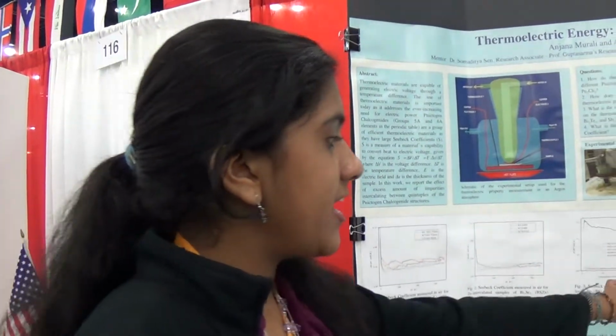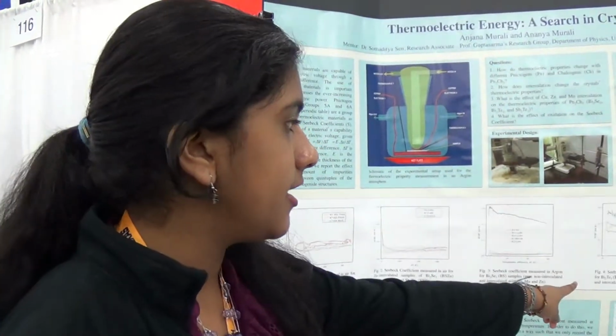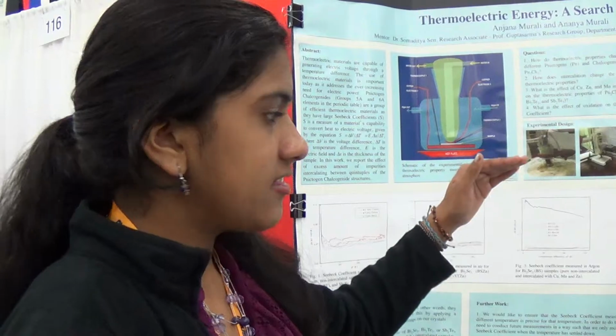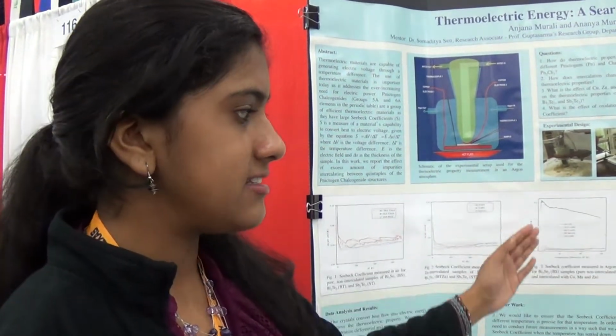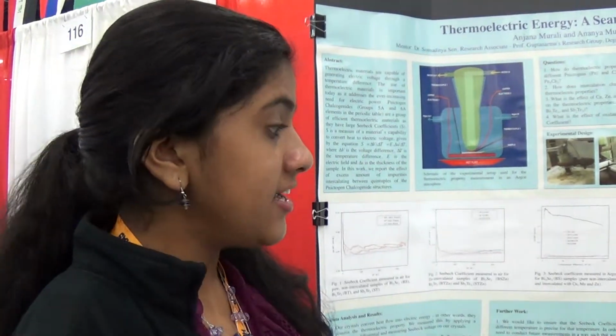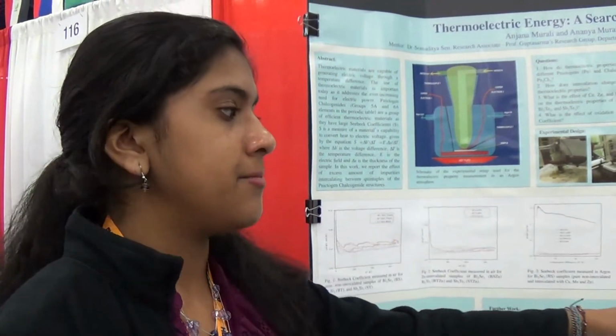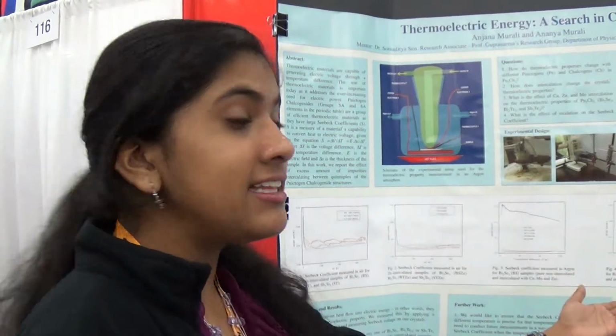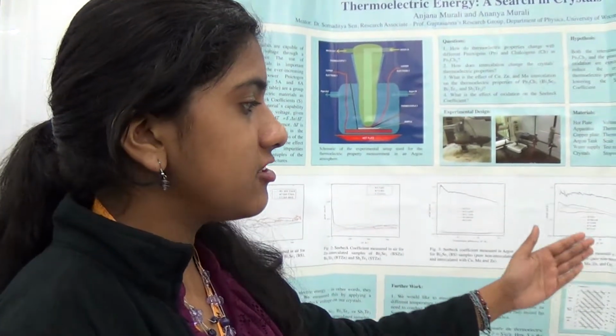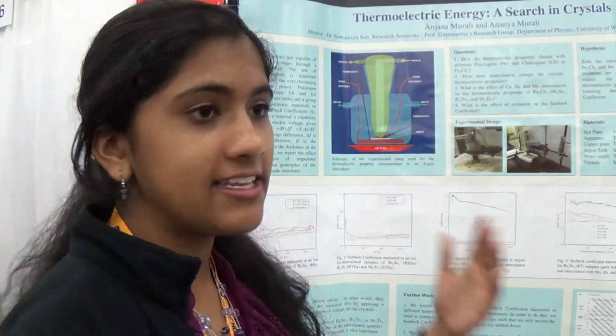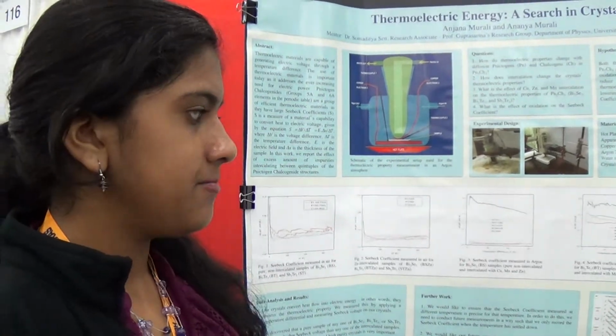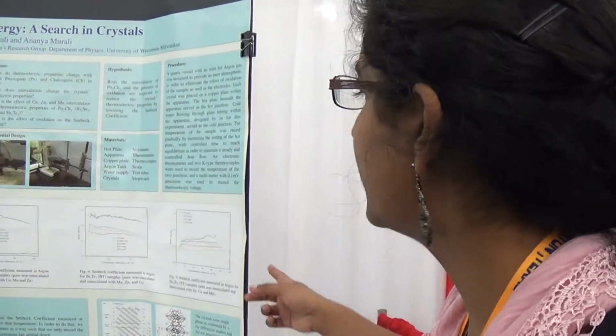And we saw the same trend in all 3 graphs, but in bismuth selenide and bismuth telluride, the graphs either leveled off or even decreased, giving a negative slope as the temperature difference increased. But in the antimony telluride system, we saw a slightly different trend where the graph actually increased as the temperature difference increased.